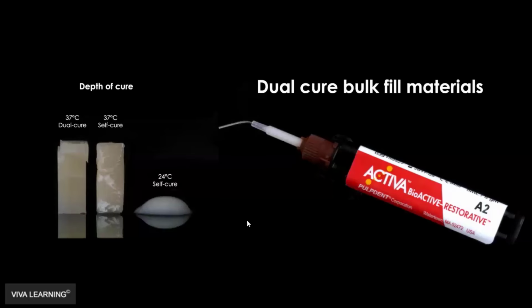And one of the things I like about it is it's a dual cure bulk fill material. I just love dual cure bulk fill materials because they've got this kind of unlimited depth of cure. So if I have a large filling that's somewhere in between a filling and a post buildup almost, that probably should be a crown, this is great because it saves so much time in filling it in. Even as a medium-sized restoration, the other nice thing about this kind of dual cure bulk fill is that I don't have to worry about voids between layers.